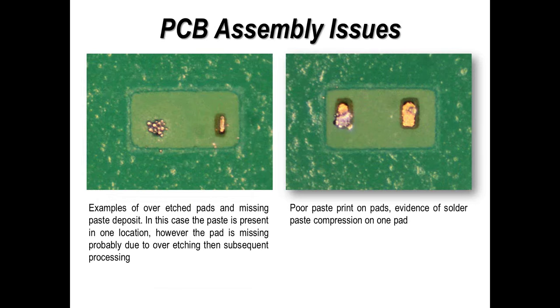So even in the PCB fabrication stage, we can lose pads either by pressure of jets during the etching process if they're not connected to anything else, but certainly mechanical handling can have an impact. And on the right hand side, we see poor paste printing, but we can still see some coining of paste onto the surface of the pad, and on the second pad on the right hand side, you can see just one particle of paste. It's interesting, when you get down to this sort of size, it's not volume of paste, it's number of balls per pad that you tend to see,